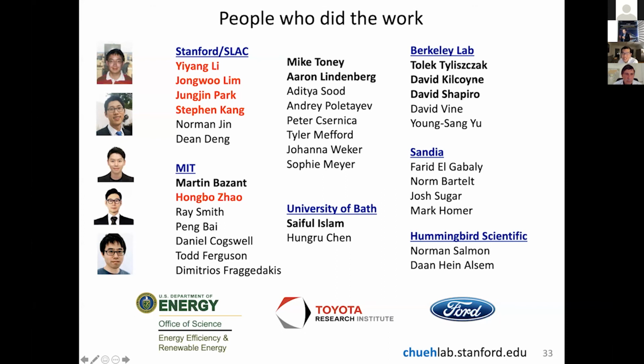Hi, Wucha. It's good to hear your question. So this is a great question. So why does the reaction kinetic depend on composition? This is really just a very simple consequence of point defects. So in order to insert lithium, you have to have lithium sites on the surface. So typically, the more lithium sites you have, the faster the kinetic. So this is really just a direct reflection of the active sites. And when we change the composition of the material in the battery, we're changing the active site on the surface, and therefore the kinetics change. So this is a very straightforward effect of composition on the kinetics of intercalation.